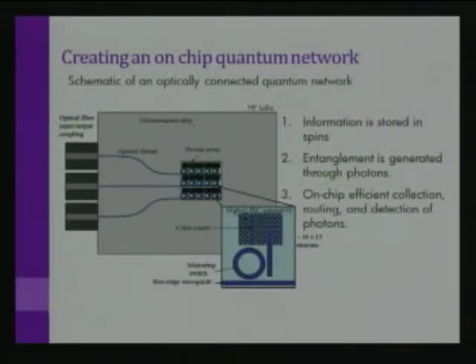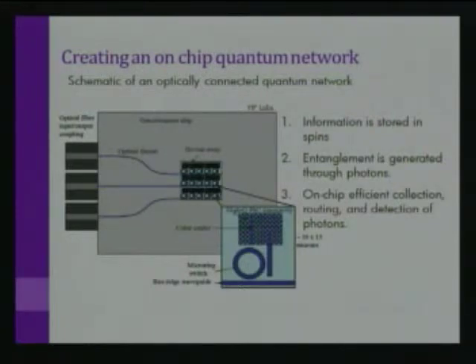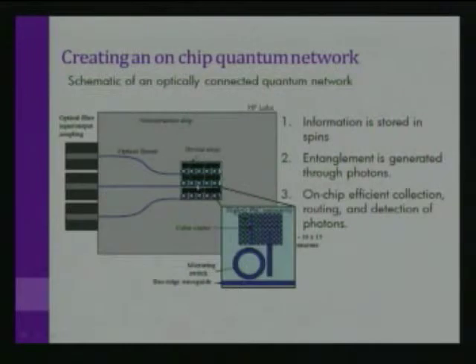We have a color center in diamond emitting a photon coupled to a spin. It goes into a micro-ring switch and, as shown in the earlier diagram where all cavities are micro-rings, it can interfere with photons from other spins and create entanglement between spins located at each of those cavities. One material system I'm working on in my lab is the nitrogen vacancy center in diamond. In the diamond lattice, you remove two carbon atoms — in the place of one you put a nitrogen atom and leave the other vacant. This is one of hundreds of color centers that exist in diamond.